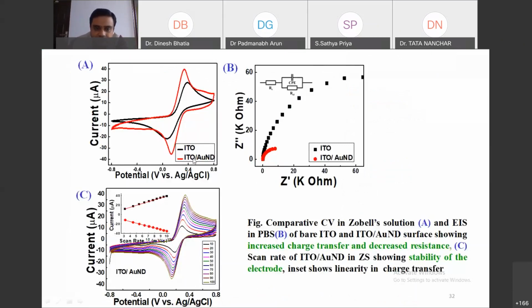You can see very clearly in the black and red curve that electron transfer, or the data output here, is less compared to the formation of the 3D structure. The signal output in terms of the current is very high. It means the surface is conducting, and when we check the complementary data with reference to the resistance, the red has a lower resistance. It is something about 28 kilo ohms, and in this case the current is relatively higher. So these two data complement each other. It shows that the 3D structure formed onto the surface is working very well, and this data is related to the stability that I will not go into in detail.